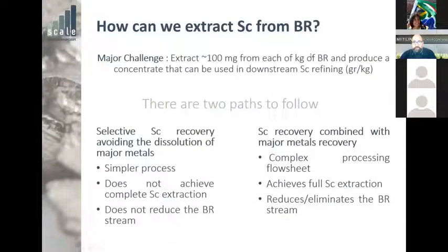And the big question now is, how can we extract scandium from these resources? The challenge we're facing is that we have to extract 100 milligrams of scandium from each kilogram of bauxite residue, in such a way that we can then produce a concentrate that can be used in refining scandium. So we have to go from the milligrams per kilogram scale to the grams per kilogram scale. The same is true for the other rare earths if you want to extract them. You cannot start with such a low concentration. You need to get grams per kilogram.